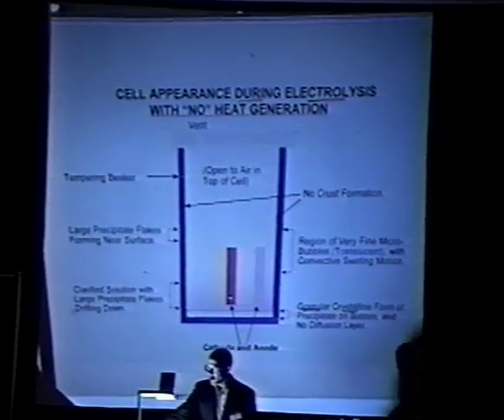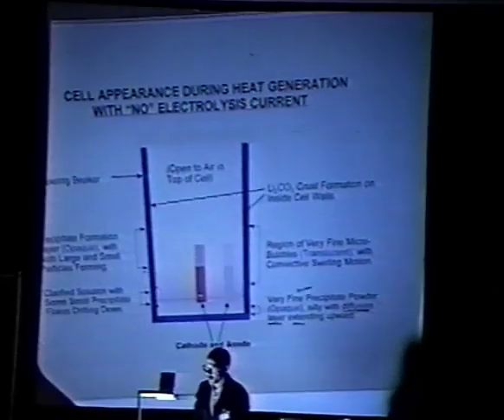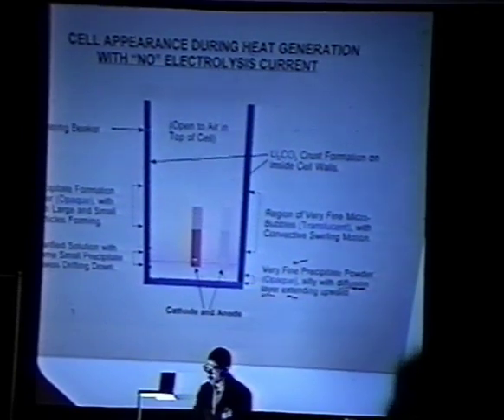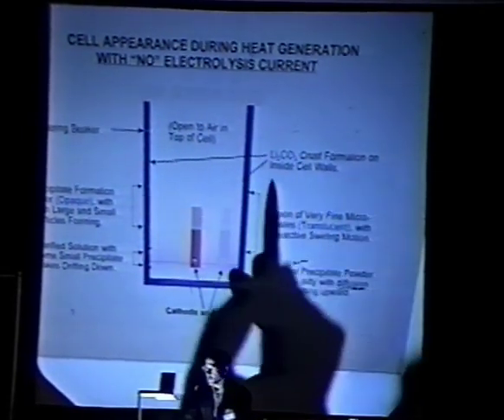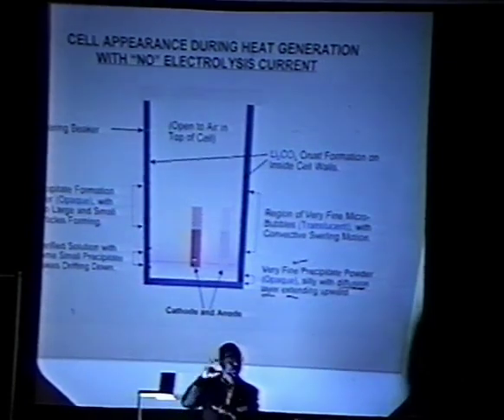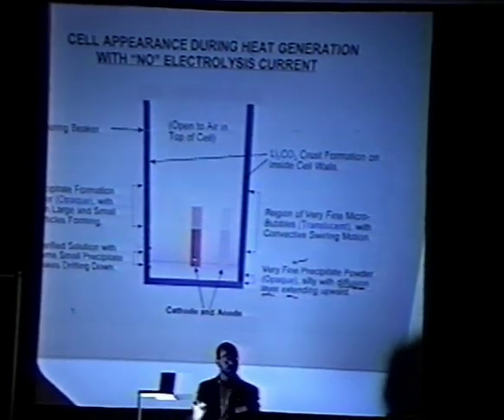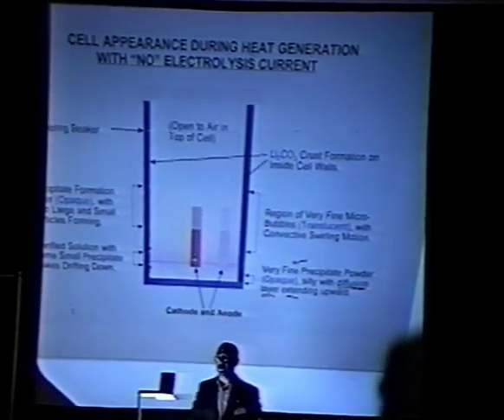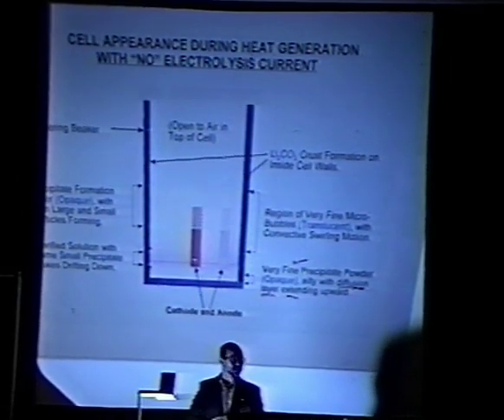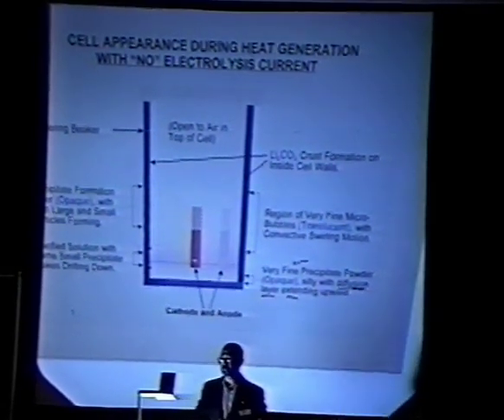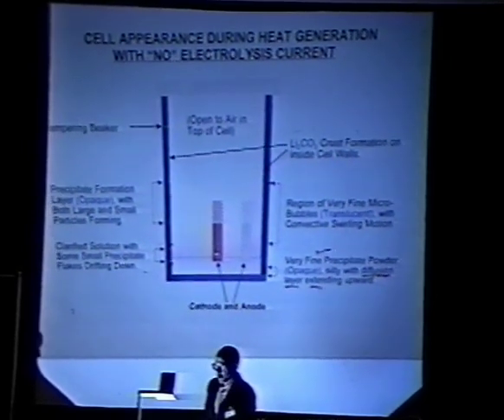Whereas those that produce heat, the top of this cell becomes very crusted. In fact, I mentioned it here, the lithium carbonate crust formation on the inside walls. That crust forms and creeps all the way up to near the top and also coats all the wires and cables that are running up there. Completely different than those that are not producing heat. Again, I can't explain it, I'm not a chemist, but I'm just showing what I observed on this. Quite interesting and quite surprising to me when I first saw a lot of this. Okay. But anyway, there are drastic differences between running it with current and without.